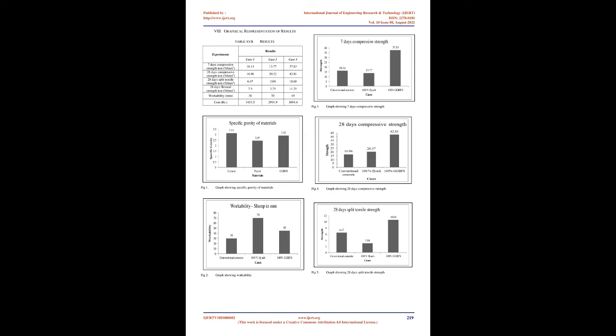7. Cost analysis. Cost analysis is a summary of all the costs involved in doing particular work or unit work. In this project, Case 1, conventional concrete, Case 2, 100% fly ash, and Case 3, 100% GGBFS, are cast. The mix design for M30 geopolymer concrete was derived and obtained a mix ratio of 1:1.3:3.1. NaOH solution, 10 M, and Na2SiO3 solution, 50.32%, are required in Case 2 and Case 3 for the polymerization reaction.